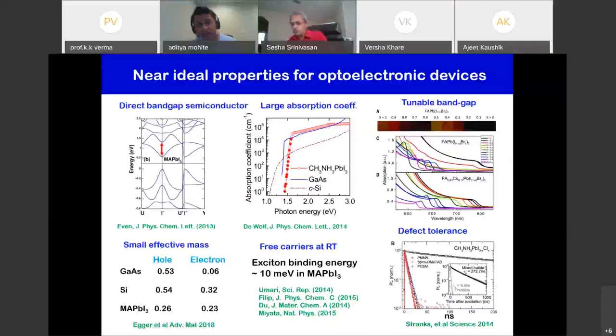And so this means that these carriers, the electron or the hole, move around and are present in this material for a long time, and they don't really get lost. That's a really unique property, because most of the time when you have defects, you lose these carriers very, very fast. And so that's what makes it special.